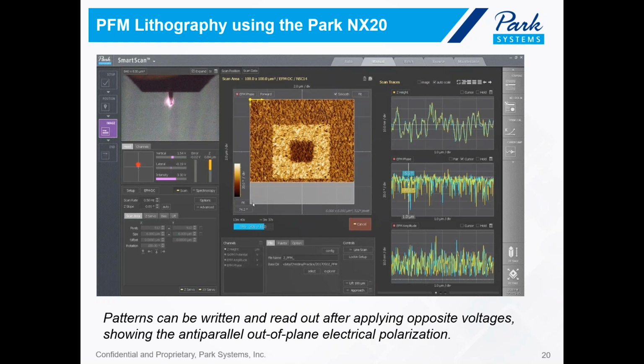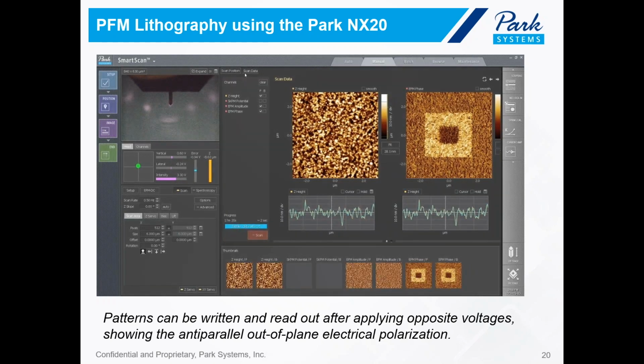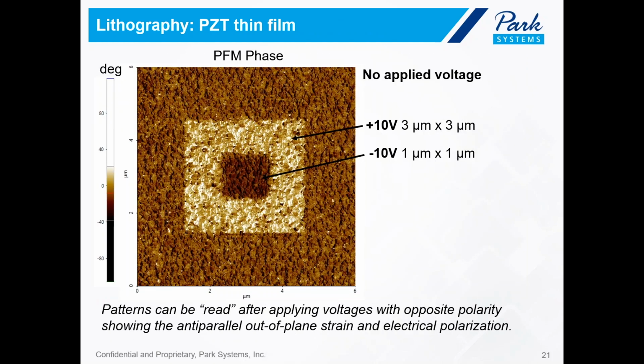So clearly, we can see that we have 3 different regions, 3 distinct regions of intensity in the PFM phase signal. So just to look at this image once again, this is a PFM phase signal, and you can see that there is a brighter region right here, which corresponds to that 3 by 3 micron scan written with the positive 10 volt tip DC bias.